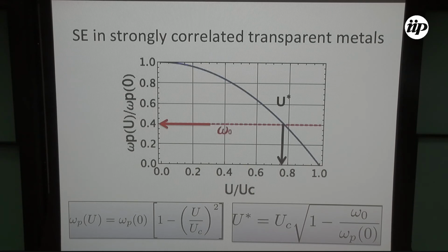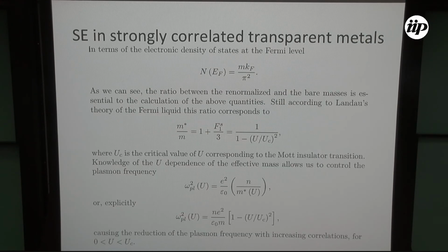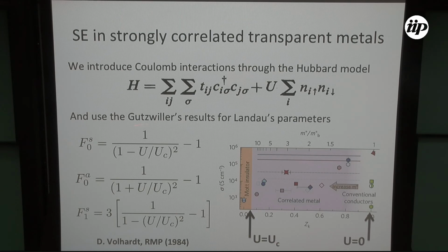No, this is done at zero temperature. So, the results for the Landau parameters from Gutzwiller. There's also the Brinkman and Rice paper where they show that it's general for different filling. There is one modification. If you put a huge bracket here, there is a numerical constant that away from half filling is 1.08, something very close to 1. So we are considering that this constant here is just 1, and we are moving forward. This is Gutzwiller: you write down a wave function and you do a variational approach. And they even get the Mott-insulator transition. But I'm not going to go beyond U critical.